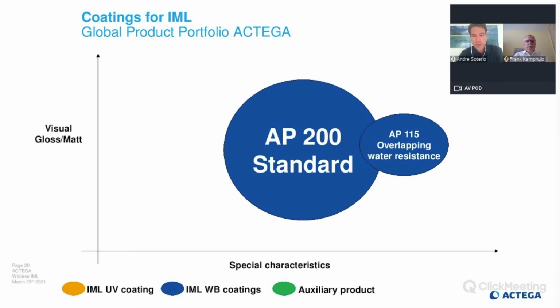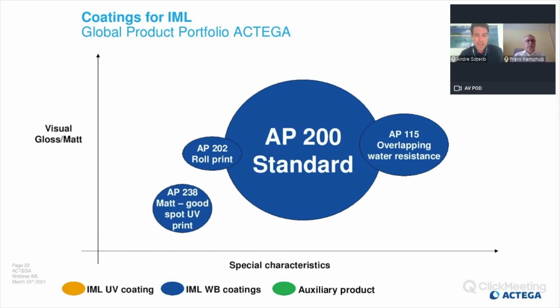We have some products with a little bit more resistance, like overlapping and water resistance. That's a product called Aquaprint 115. The Aquaprint 202 is for row printing, like UV offset row to row, and then water-based coating at the end. Then some matte products, very good for spot UV printing. You print a matte coating on the 100%, and then use it with a UV spot printing to have a matte gloss effect. Then we have the Aquaprint 215. It's a high gloss coating, but as I said, it doesn't reach such high gloss compared to a UV coating.